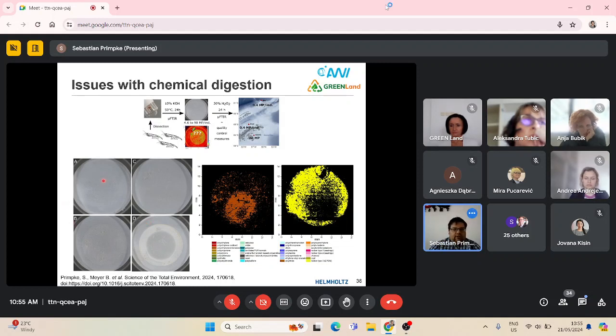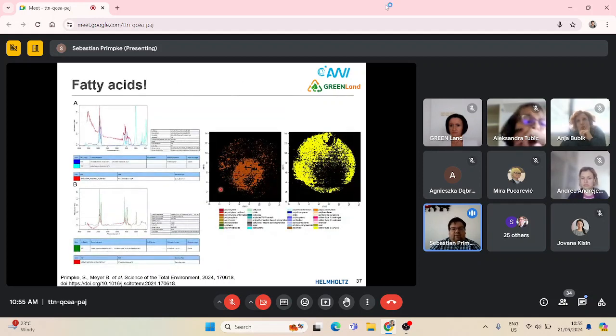but even at low numbers. Then we checked all of our chemical digestants, and some showed these kind of mega particles, which really hinted at a film-like structure. We investigated this and figured out that these two types of films are linked to different types of stearates. So we had the fatty acids still in our sample, and they could form a thin film on our particles, hampering or overlaying the analysis. So we had a high number of false positive results, and then we figured out what we could do.